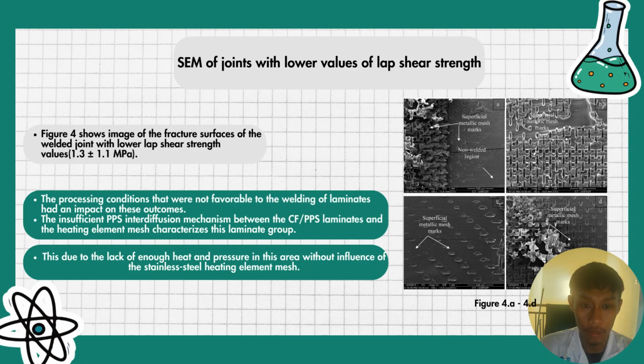SEM of joints with lower values of lap shear strength. Figure 4 shows an image of the fracture surface of the weld joint with lower lap shear strength values, which is 1.3 plus minus 1.1 megapascal. The processing conditions that were not favorable to the welding of the laminate had an impact on these outcomes. The insufficient PPS interdiffusion mechanism between the carbon fiber over polyphenylene sulfide laminate and the heating element mesh characterizes this laminate group. This is due to lack of enough heat and pressure in this area without the influence of the stainless steel heating element mesh.